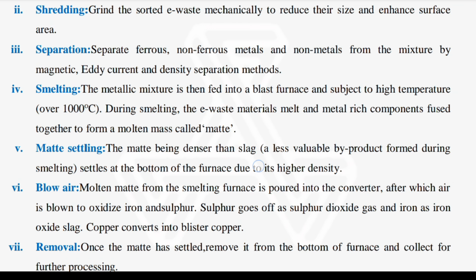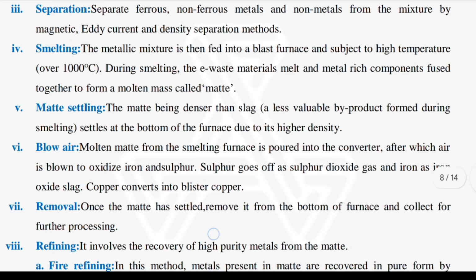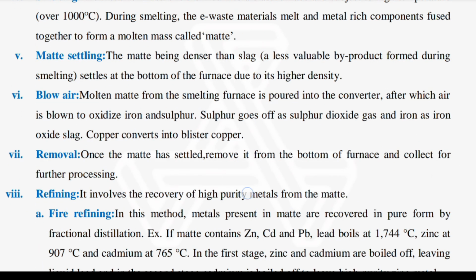Blow air. Molten matte from the smelting furnace is poured into the converter, after which air is blown to oxidize iron and sulfur. Sulfur goes off as sulfur dioxide gas and iron as iron oxide slag. Copper converts into blister copper. Removal. Once the matte has settled, remove it from the bottom of the furnace and collect it for further processing.